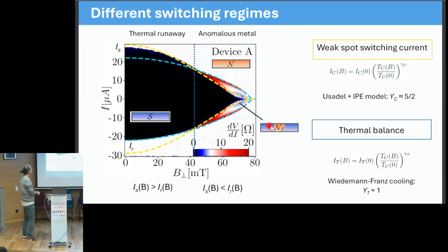First, once we generate this normal spot, it has a resistance, so when we're running current, this normal spot will start dissipating heat. If my normal spot dissipates more heat than I can dissipate with my device, this leads to what we call a thermal runaway. As soon as this normal region nucleates, it will expand and transition the whole wire to the normal state. But in other conditions, when the critical current is lower, the heat dissipated by the normal spot will be lower than what can be dissipated by the device, and we stabilize a normal phase. Okay, and this, we now understand, lies at the origin of this anomalous metallic phase.